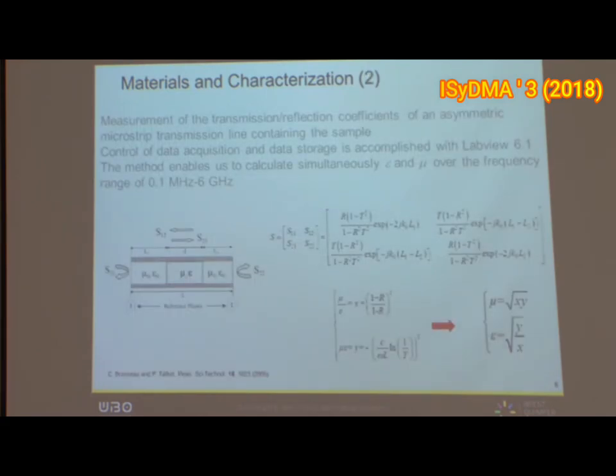So basically, to measure the electromagnetic response, we use what is called the transmission line system. We basically put the sample in this, so we create an electromagnetic discontinuity in this line. And what we measured is a reflection or transmission coefficient called the scattering parameters, which are represented by this matrix.